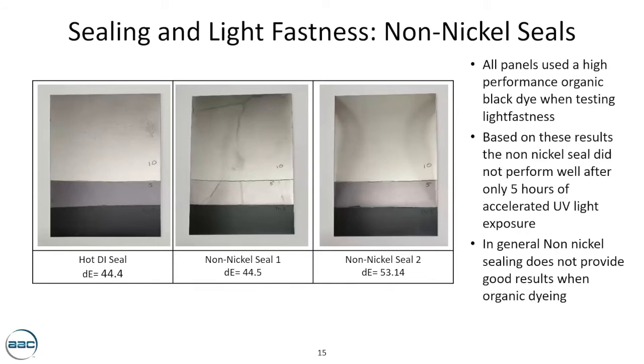Now, we will look into the last topic, light fastness with the seals. The first one is the non-nickel seal, where we used 3 different seals, a hot DI seal and 2 non-nickel seals. The panels used for this test were produced using a high performance organic black dye. You can see based on the results that the non-nickel seal did not really perform that well after only 5 hours of accelerated light fastness test. You can say that in general, non-nickel sealing does not provide us with good results, especially with organic dyeing.